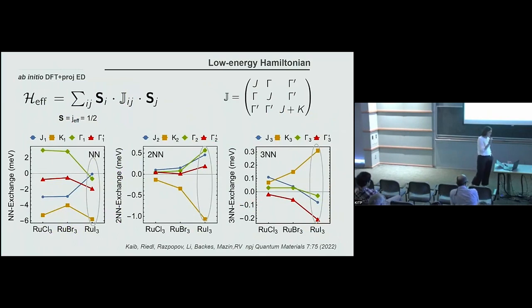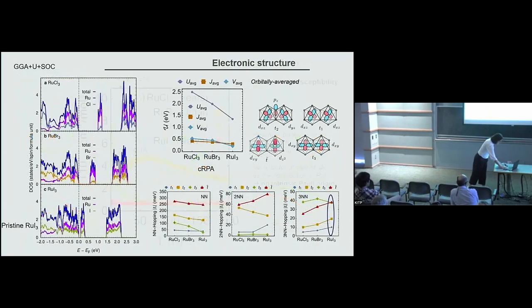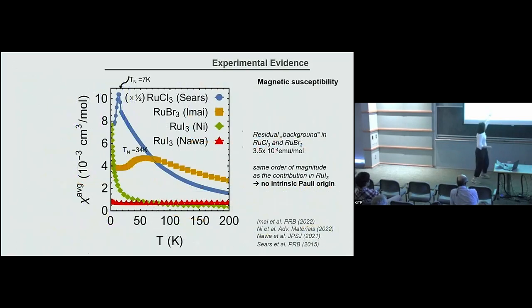So indeed, the reason for these temperatures, and in fact, if you look, it's very interesting, the phase transition is not as sharp as in the ruthenium trichloride, but the reason for these temperatures is indeed the combination of interactions that you have in the system that push the system, in fact, to order.